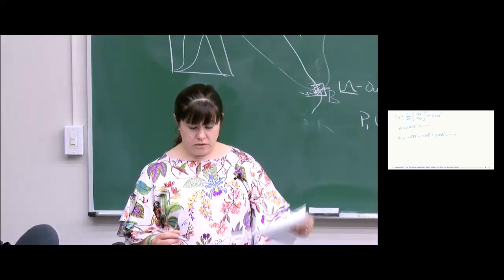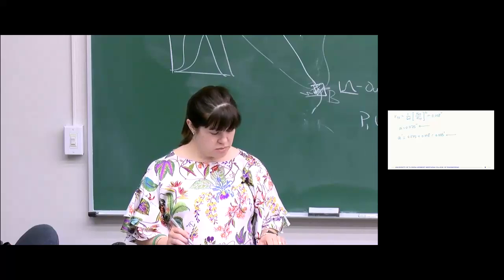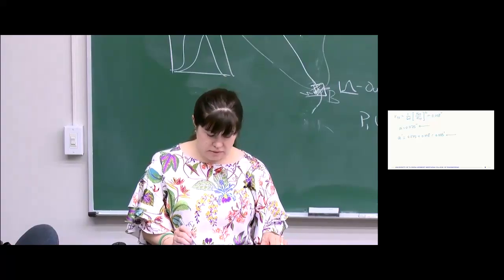And so all we have to do is go back and change what's in our integral. So if we set it up, on the left side was -2 divided by our critical crack length, 0.28. And then all we do is add this, instead of 0.075, it's 0.083. And then the right-hand side is the same.